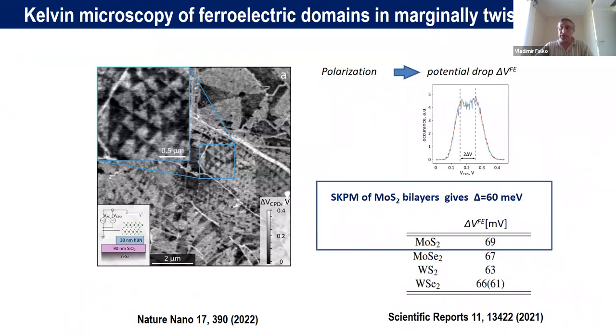So this has been done and tested, and what you see here is statistics obtained on multiple domains in different parts of the structure with different local misalignment angles. And what you see here in this histogram built from this obtained data is the value of twice this delta, which reasonably well corresponds to what we calculated in density functional theory. The experiment gives something like 60 millivolts for delta, and in the DFT for molybdenum disulfide, which was studied in this experiment, it was obtained about 70 millivolts.